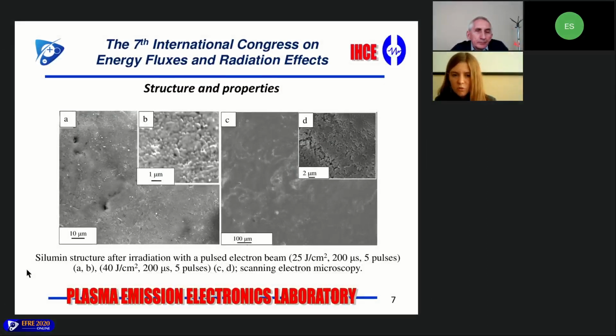The treatment of silumin with an electron beam with an energy density of 25 joule per square centimeter and higher is accompanied by melting and subsequent high-speed crystallization of the surface layer. A dispersed structure is formed. You can see it here. Micropores and microcracks are melted, so we see the smooth surface with cellular structure.